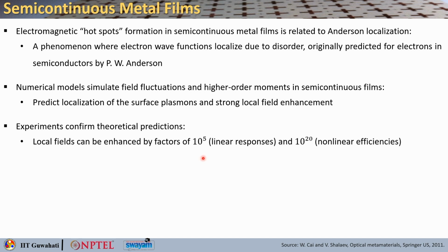local fields can be enhanced by a factor of 10 to the power 5 in the case of linear responses. If there are some nonlinearities involved, you can go even up to 10 to the power 20. So that is like a huge enhancement, and you can take help of that local field enhancement to do sensing of trace amounts of molecules, typically using surface enhanced Raman scattering kind of applications, where you can do ppb, parts per billion level of sensing, which is otherwise impossible to do.